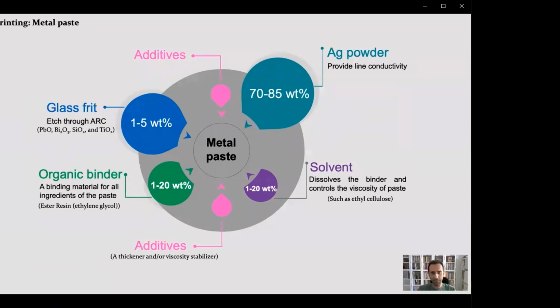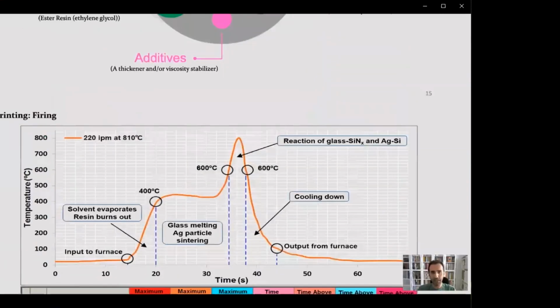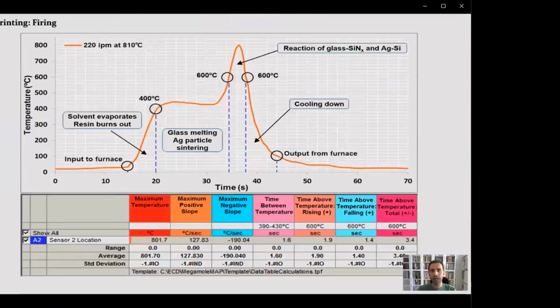After the pastes are printed on both sides, the cells need to be fired at high temperatures up to 810 Celsius degree, 820 Celsius degree, so that metal makes a contact with the emitter. This is a typical firing profile that is used in the manufacturing. Starting from room temperature, the cell enters the furnace, usually below 500 Celsius degree.